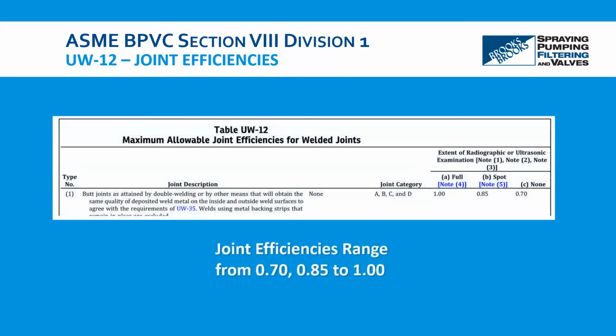The next concept we need to be familiar with is joint efficiencies. And you'll have seen this actually used in the previous calculations. The variable in this case was E. This determines the material strength. Joint efficiency is used as a measurement of the welded joint with respect to how close it is to its material strength. And without implementing certain tests or inspections, the joint efficiency of a welded joint is actually less than the parent material. And it's something that, per conducting tests, you're able to bump that joint efficiency up by verifying the weld. And we'll see how this applies in a bit as it relates to radiography.